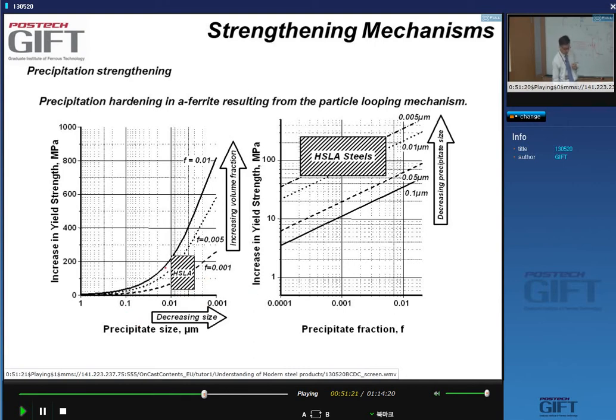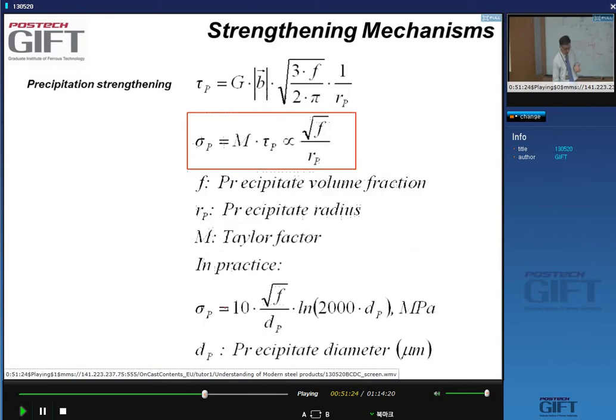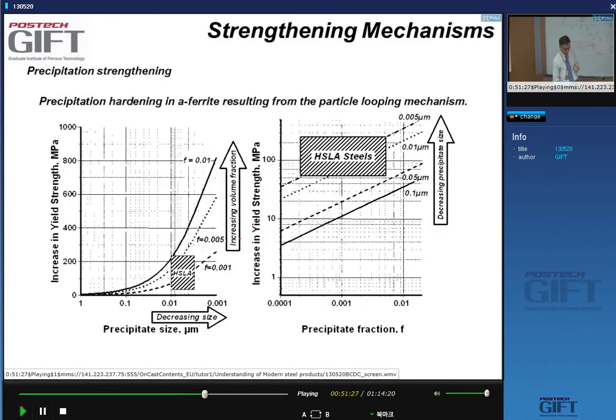And you can present this equation, that's this equation here, also as increase in yield strength as a function of the precipitate fraction, for different radii of the sizes of the precipitates. Now, typical values are 5 to 10 nanometers, yeah, 5 nanometer particles. We can see that if your volume fraction is 10 to the minus 3, the strengthening will be about 100 megapascal, yes?